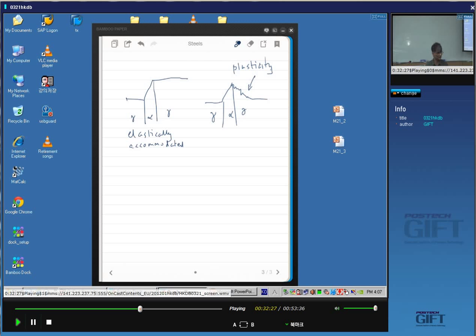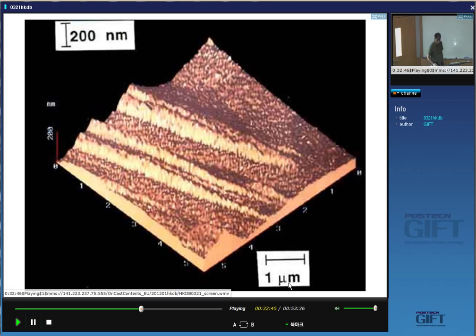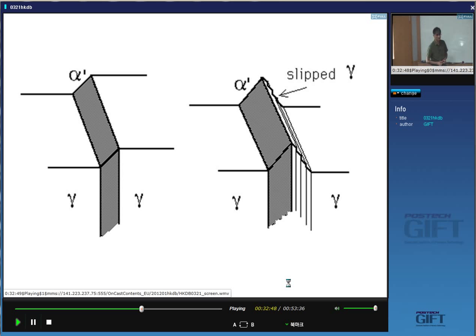That means you get very, very fine plates, much finer than with martensitic transformation. So that's a good thing from the point of view of structure-property relationships. And I'll show you a transmission electron micrograph of the structure at the interface between bainite and austenite. So this is the diagram that I just drew out, where we are looking at plastic accommodation in the adjacent austenite. And of course, one more very important thing is that if the bainite grows into this region, then there will be a large orientation gradient within the bainite, because its dislocations produce misorientation.